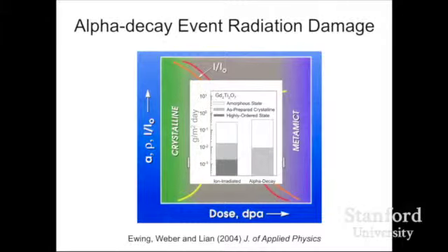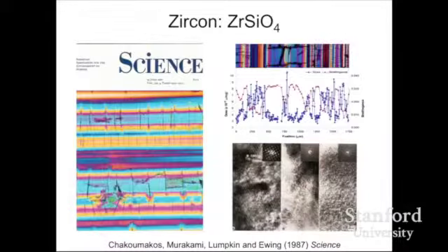Okay, this transition from crystalline to amorphous, sometimes called metamict, the important point is it changes the solubility, the release rate, by one or two orders of magnitude. So we can make very durable solids with actinides, with plutonium, but it turns out that nothing's ever as simple as it looks in the first moment. The radiation damage matters quite a lot.